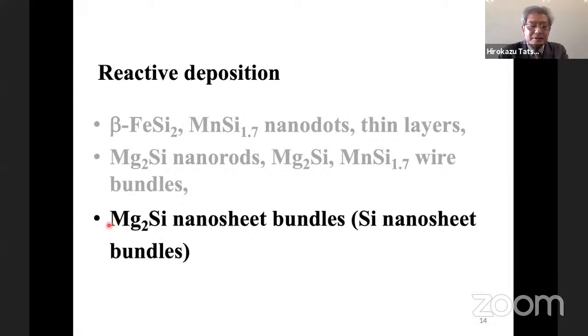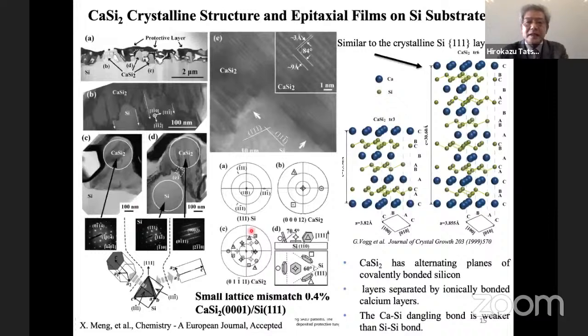Next, I would like to introduce magnesium silicide nanosheet bundle formation. To make silicide nanosheet bundle structures, we use calcium disilicide as a template material. This calcium silicide has such a crystal structure. It is hexagonal, and along the C direction, layers are alternately stacked: calcium layer, silicon layer, calcium layer, silicon layer. And there are some polymorphs. So if we can extract the calcium layer only, we can make a silicon nanosheet.